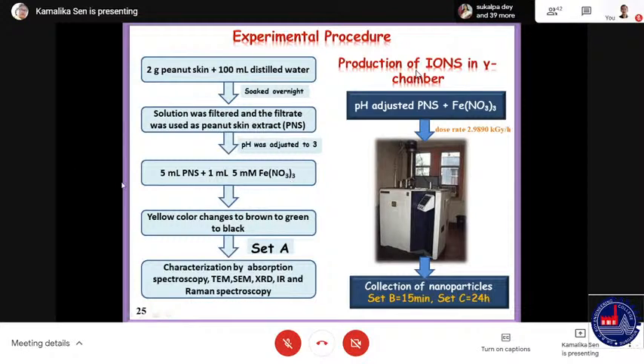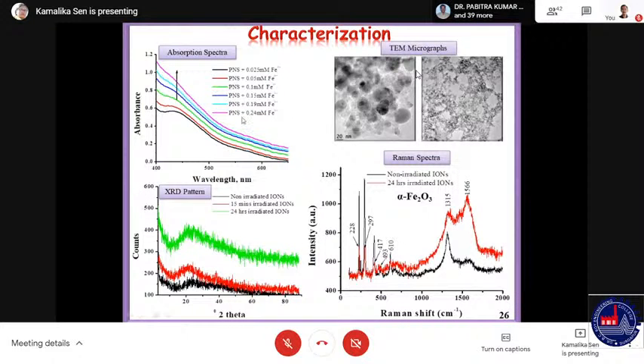the application of gamma irradiation. Similarly, if set A is put inside this gamma chamber for 15 minutes, we call it set B. And if we keep it inside the gamma chamber for 24 hours, that is called set C. At the time of irradiation, the dose rate inside the chamber at UGC-DAE CSR Kolkata was 2.989 kGy per hour. So the UV spectrum of the solution that we have used after adding iron shows the characteristic surface plasmon resonance at about 430 nanometer, which is its characteristic peak, and it increases with increasing concentration of iron.